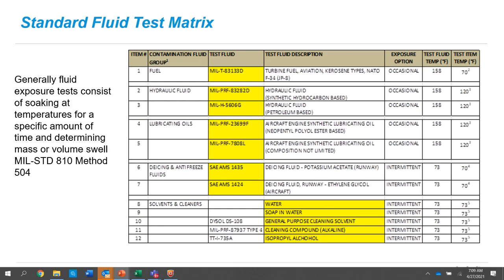So all of these, usually the test is a soak test. You'll take the material, soak it in there at a certain temperature for a certain period of time, and you'll look at volume or mass swell of the material. And then of course you'll look at the performance of the material before and after. So those are kind of the two things. If the elastomer, or the polymer, is going to be subject to swelling due to incompatibility with these materials, then that could also affect the performance of the filler inside. So a lot of fluid testing that we do, and we do this in-house as well as through subcontractors.